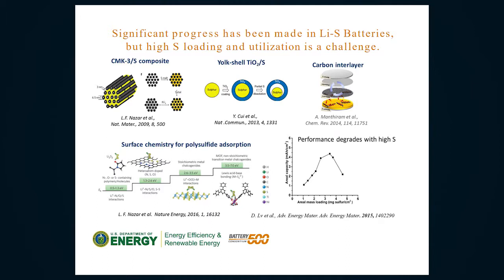Indeed, if you do this, it all helps. They really reduce the dissolution. You can get really nice data on the electrode material. But for the whole cell, it's really a different story. Not only is nanostructured carbon expensive, but it comes with a lot of porosity and surface area. That means you are significantly reducing the amount of active material. Also, you make this all work very nicely with thin electrodes, but if you make real cells, it doesn't work. When you make thick electrodes, they just bomb.